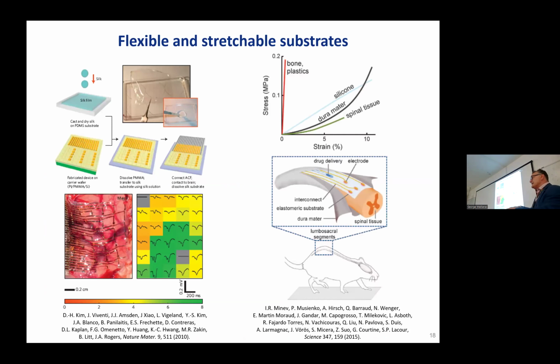And it's intersecting another technology, which is that of large, flexible and stretchable substrates. What do I mean by that? These are two examples of that work. This is from the US, the group of John Rogers, who developed large area substrates that are so thin that you can put electronics on it, but if you pick it up to put it on the brain of the patient, it will collapse under its own weight. So they had to develop technology by using sacrificial silk films to allow you to pick it up and transfer it and then dissolve the silk away. And that leaves you with a tattoo-like structure that follows perfectly the curvature of the brain.